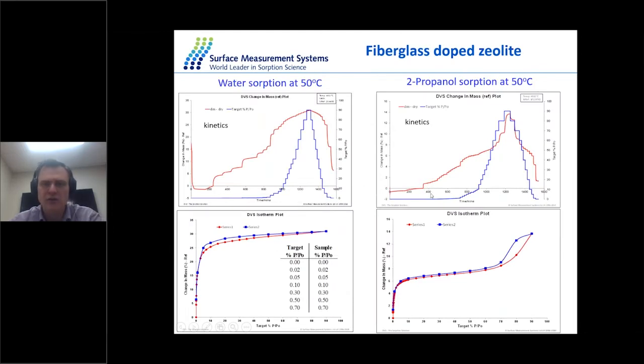Okay, now let's look at the data. What does it look like? Here is the typical adsorption kinetics for 2-propanol at 50 degrees for a fiber zeolite. You can see this extremely low P over P naught. The solid blue line is the partial pressure plot, and the solid red line is the mass. The partial pressure plots you saw in the previous slides. At extremely low partial pressures of 2-propanol, I can still get a really good mass signal. If you convert this data to isotherms, you get nice type 4 isotherms with lots of data points in the region of condensation limits of porosity.